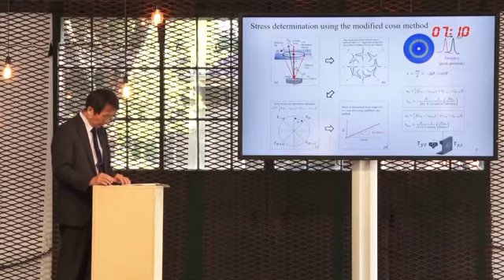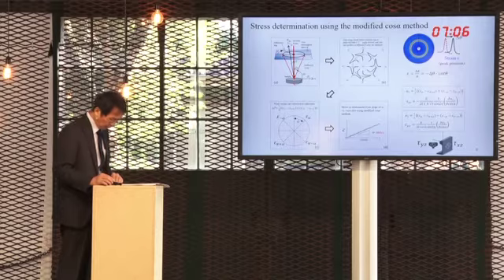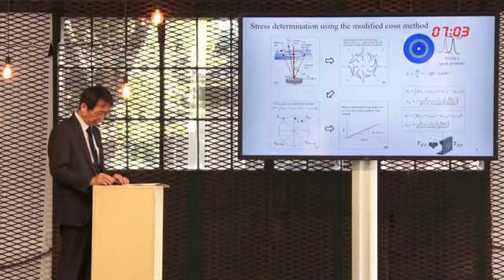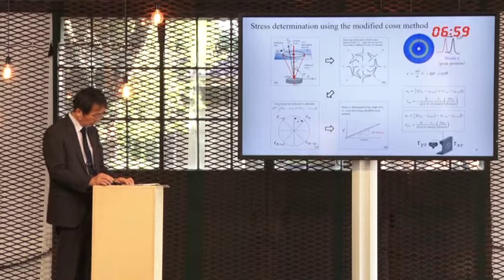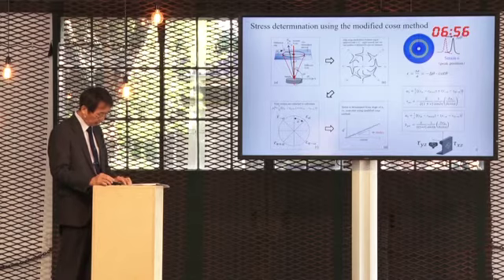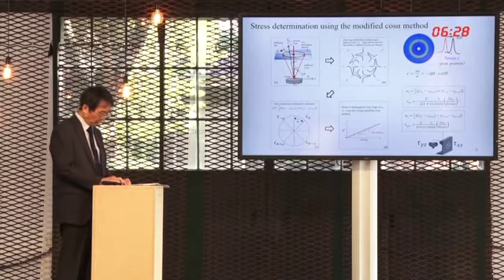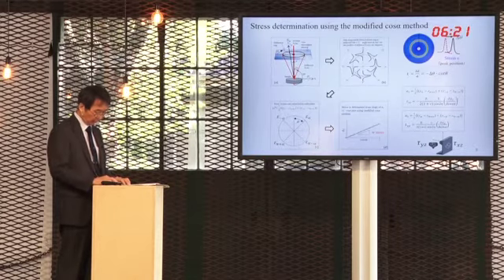At the next step, we calculate the residual stress from strains obtained from the diffraction ring. This slide shows the process for determining strains and stress from the diffraction ring. The so-called modified cosine alpha method was used for stress determination in this study. When using this X-ray optics, we can obtain the 2 kinds of triaxial shearing stresses, tau xz and tau yz, where x is the axis parallel to the running direction of the train. The y-axis is the transverse direction of the rail, and the z-axis is the depth direction.